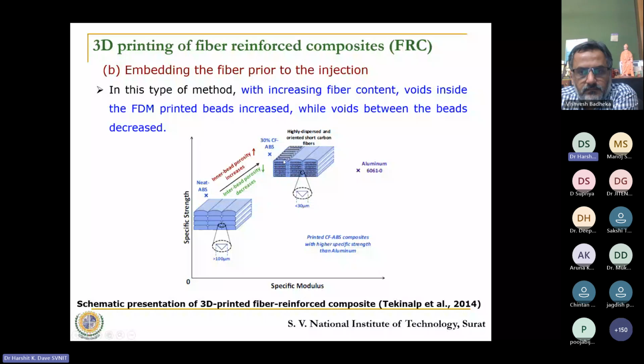So what happens over here, there is a very good observation that when the filament is pre-mixed with carbon fiber, and when these rasters are created, we observe that the interlayer gap, the void that is generated, the size of that void reduces from say 100 microns to 30 microns, because of which the strength of this part increases.